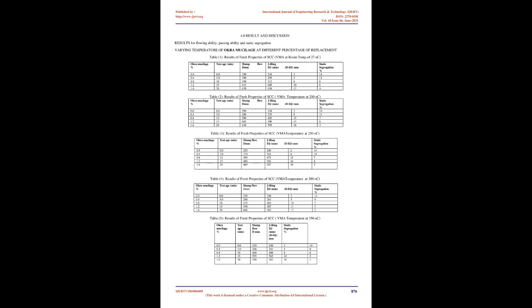During the 1 minute waiting period, the inner surface of the cone and the test surface of the base plate were pre-wet using the moist sponge, and the cone was placed in the center on the 200 mm circle of the base plate, and the weight ring was put on top of the cone to keep it in place. If a heavy cone is used, or the cone is kept in position by hand, no weight ring is needed.